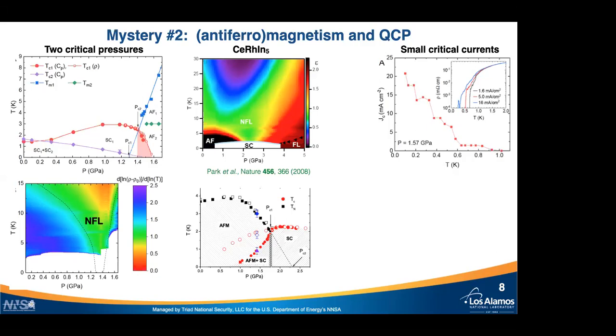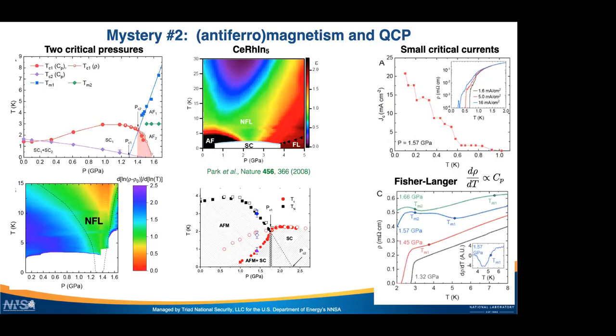First, if we have two transitions, that is inconsistent with a simple ferromagnetic state. If you have a ferromagnetic state, you already break that symmetry. All the spins are pointing towards one direction. Maybe you can have a rotation of the spins, but that would be a crossover. It wouldn't break any additional symmetries. But here, clearly, we see two peaks in heat capacity and anomalies in resistivity.